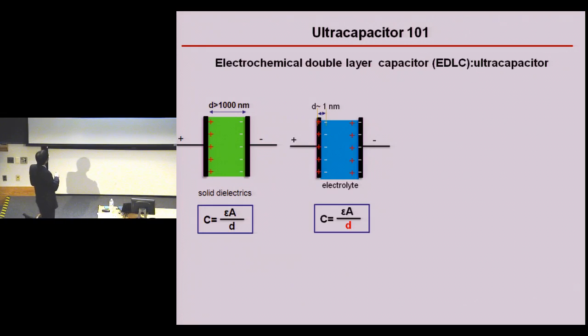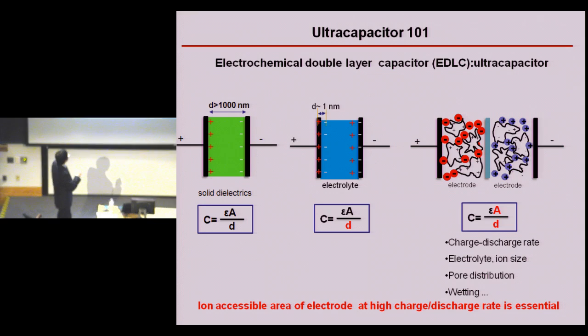If we change the solid dielectric to electrolyte, the charge separation will be very different. You're going to have charge separation at the interface of the electrolyte and the metal. And basically, you have two capacitors in series. Because the charge separation at the interface is at a distance of about 1 nanometer, you dramatically decrease the distance compared with the solid dielectric-based capacitor. That means you increase the capacitance dramatically. But in real applications, instead of using a flat metal, typically people use a highly porous conductor. So that means the surface area will be enhanced dramatically. In this way, you really maximize the capacitance.